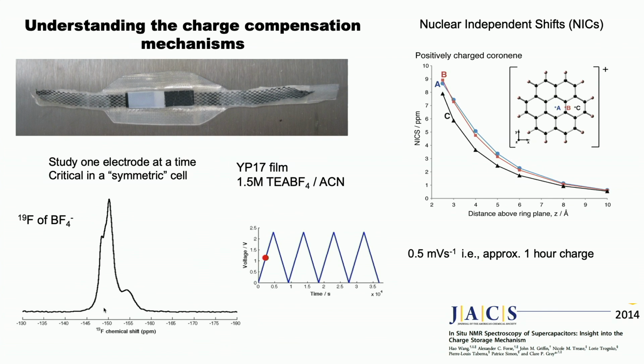And what we did with our in-situ NMR, this is now a while ago, was to ask the question, how do ions insert inside carbons? What you're watching in real time is the fluorine NMR of the anion in this salt, tetraethylammonium BF4, in acetonitrile. This is the signal as you're charging up and down, of the ions going in and out of the pores. And the signal is shifting backwards and forwards as you're inserting. In this case, we're going positively, so we're inserting holes into the system. We're charging up the carbon sheets, and we're reducing the aromaticity of the carbon.